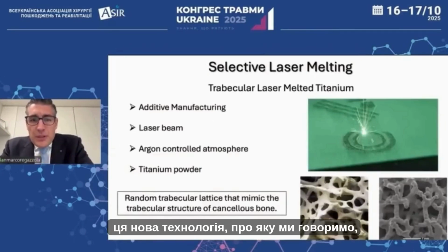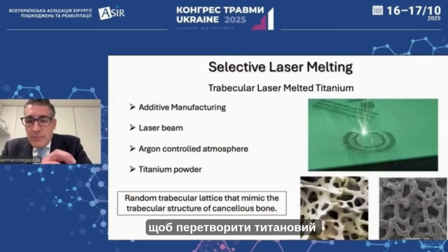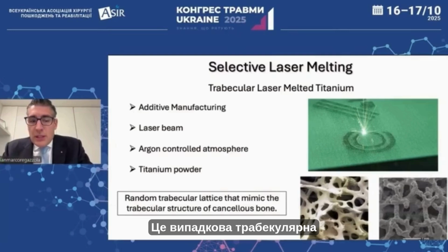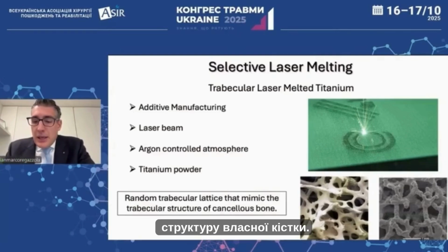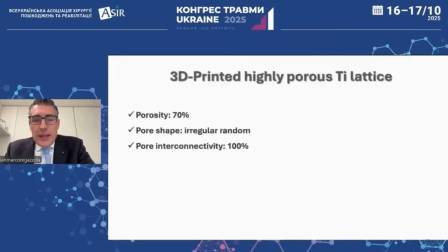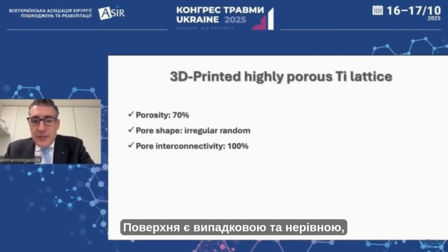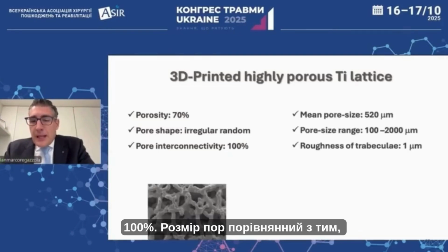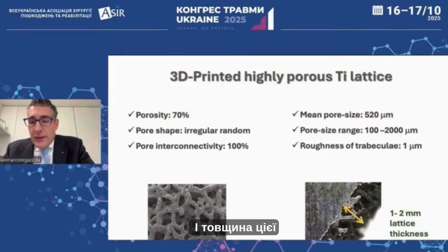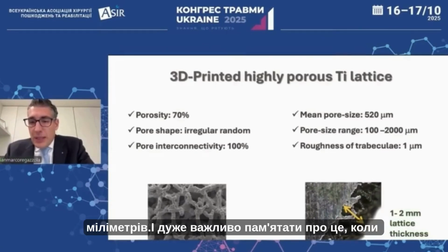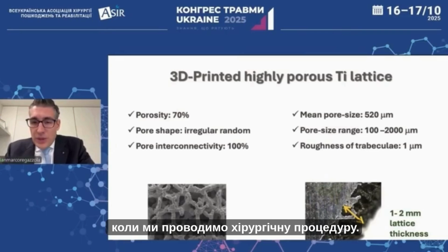So this new technology that we're talking about uses a laser beam within an argon controlled atmosphere to turn titanium powder into a random trabecular structure that mimics the structure of the host bone. It has very high porosity. The surface is random and irregular, and the interconnectivity of the pores is up to 100%. The pore size is comparable to the one the literature suggests as the best for bone integration. The thickness of this rough surface is between 1 and 2 millimeters, and it's very important to remember this when we do the surgical procedure.